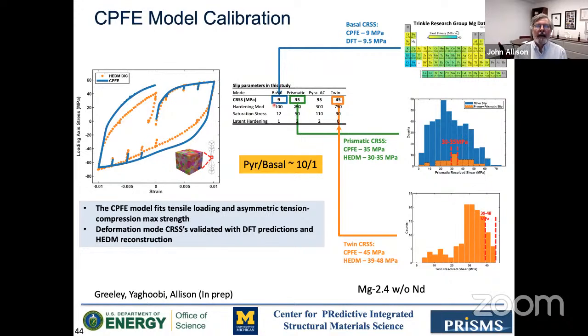cyclic stress strain. Again, now here for inputs to the crystal plasticity model, we'd love to do DFT models, but there's not very many except for Dallas Trinkle at Illinois has done it for all elements for basal, but less is known so far for many of the other alloying elements and the other slip systems. At any rate, Dallas suggests that it should be 9.5 MPa, and we chose 9. We didn't have values for these others, so we had to calibrate that from the far field results from the prismatic data and twins. The twin critical resolved shear stress you can detect as well from the far field data. And so now you see prismatic at 35, pyramidal we estimate at 95.